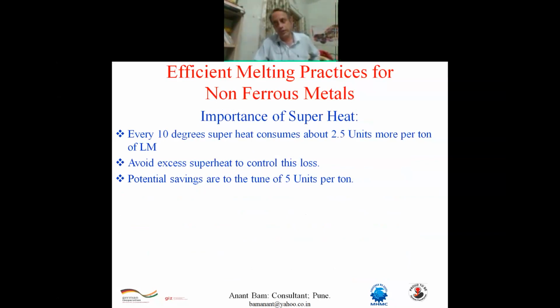Avoid superheat. Superheat is a double-edged sword. It increases fluidity, no doubt, but it consumes more energy. Every 10-degree superheat consumes about 2.5 units more per ton of liquid metal. Secondly, at superheated condition, the oxidation loss, the melting loss, is excessively high.